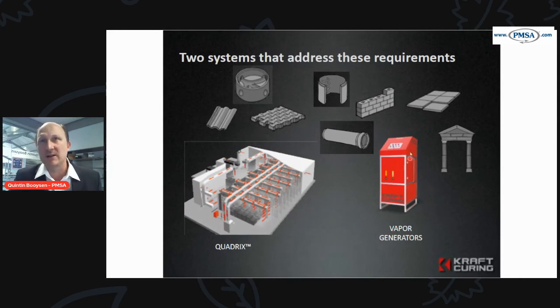And we also have a vapor generator. In the old days, people would use steam as a steam system. So you'd have a boiler and you would boil the water and generate steam. Nowadays, we use vapor, where we actually pass the water through a gas burner, and instantaneously you generate low pressure vapor, which is not dangerous because you don't have a boiler that can explode. You have a vapor, and that vapor is very easily controlled. We can spread it around systems. We can put it under tarpaulins. We can spray it into systems similar to the Quadrix, where we have a curing room. So a vapor system is ideal for modern curing solutions. And the advantage is you also have carbon dioxide inside of your vapor, which helps with reducing efflorescence.